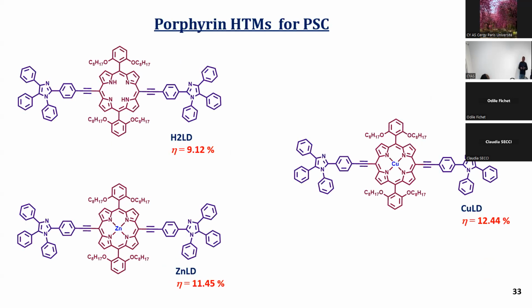In my PhD, I made three molecules as hole transport materials for perovskite solar cells. The highest efficiency was with the copper molecule, which showed 12.44% efficiency. Without a metal center, it was 9%, and the zinc metal molecule was around 11% efficiency. These were donor-π-donor triphenylimidazole based molecules.